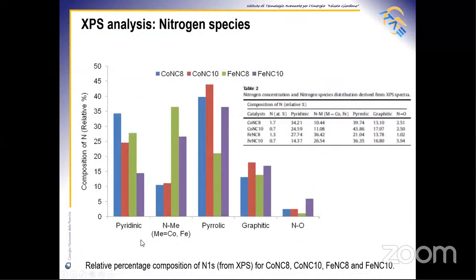By comparing the results, the amount of pyridinic N species for the CoNC8 and FeNC8 catalysts is higher than the other derived catalysts, whereas the content of pyrrolic N species increases with the catalyst treated at higher temperature. It is thought that pyrrolic N contributes to a higher production of hydrogen peroxide in the ORR process and to a decrease of the overall activity, even if the stability of pyridinic N species is compromised by the protonation of carbon-nitrogen sites in acidic environment.